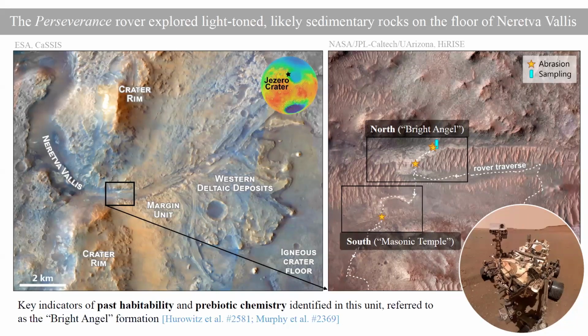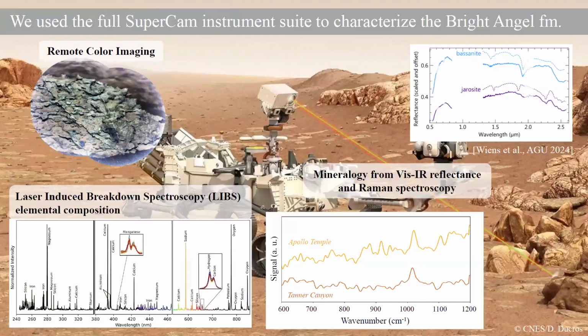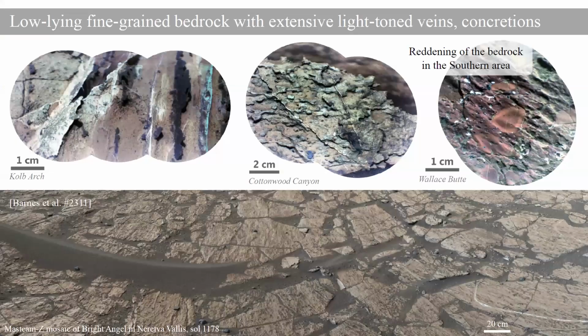If we go to the next slide, you will see that we used the full SuperCam instrument suite to characterize the Bright Angel Formation. That means frequent analysis of rock targets from about 2 to 8 meters away from the rover mast. Here we have a synergy of techniques, including color imaging, laser-induced breakdown spectroscopy, or LIBS, for elemental rock composition, and investigation of mineralogy from visible reflectance and Raman spectroscopy. In the next slide, you can see some examples of color images of bedrock exposure of the Bright Angel Formation.